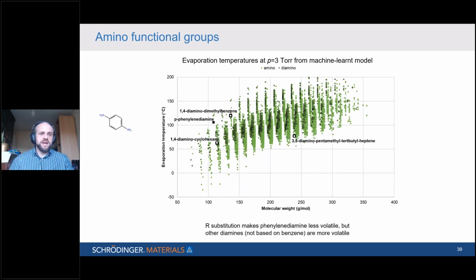Just looking at those amines, so all the molecules that have 2 amine functional groups here, if we go from paraphenylene diamine with the black dot, that's sort of the parent molecule. If we add methyl groups and ethyl groups, the volatility actually gets worse. So you can see 1,4-diamino-dimethylbenzene has a higher evaporation temperature, and the rest of that sequence are the others for us changing those R groups. So this is not the same as hydroquinone. Adding R groups makes this one less volatile.